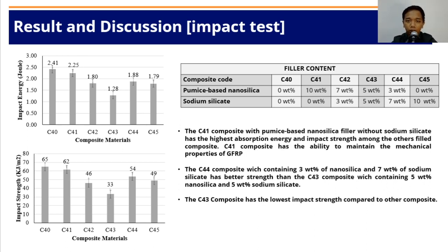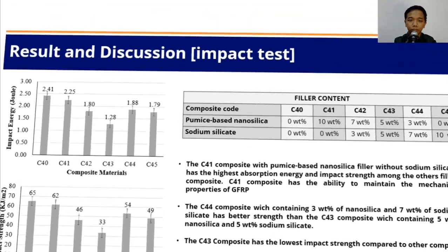The addition of nanosilica particles and sodium silicate with the same composition ratio can reduce the strength of the composite by reducing the bond strength due to powder agglomeration.